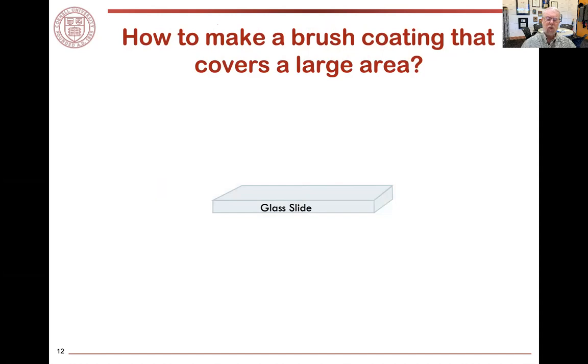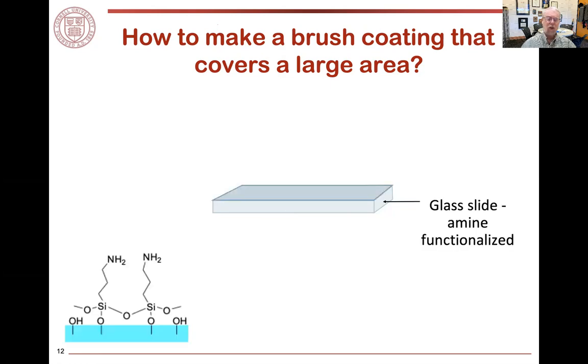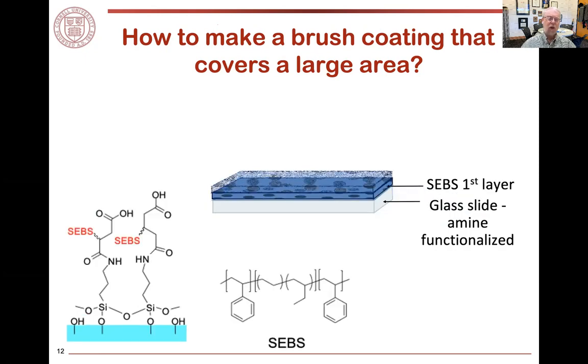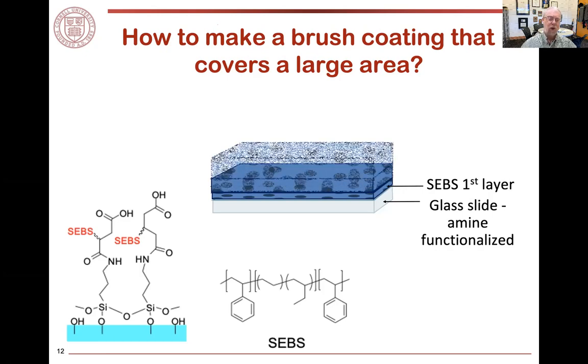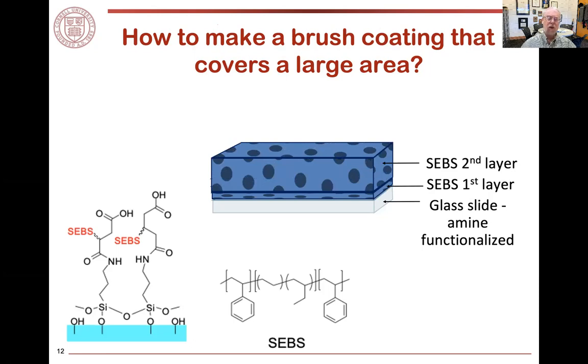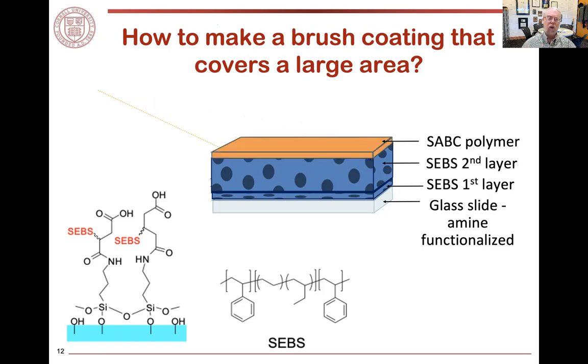Finally, by way of background, we've adopted this small sample technique and developed a method for coating glass slides using this block copolymer system. We first silanize the surface with an amine. We use a commercially available thermoplastic elastomer that incorporates anhydride groups, so we can chemically bind a layer of block copolymer on the surface. We coat a thicker layer, and the glassy phase of the thermoplastic elastomer interlocks. Finally, on top, we put a surface active block copolymer, the only requirement being that it has a common styrene anchor block. Then we can build a material that's elastomeric and easily modified in terms of surface composition.